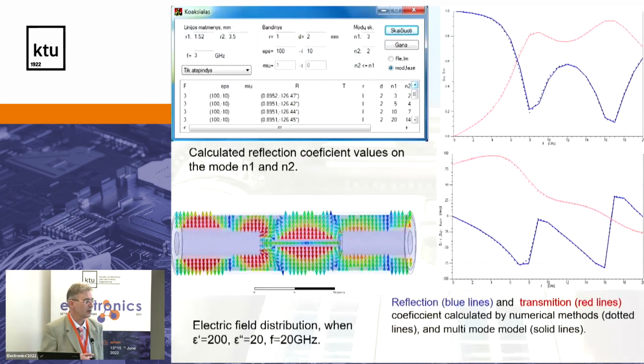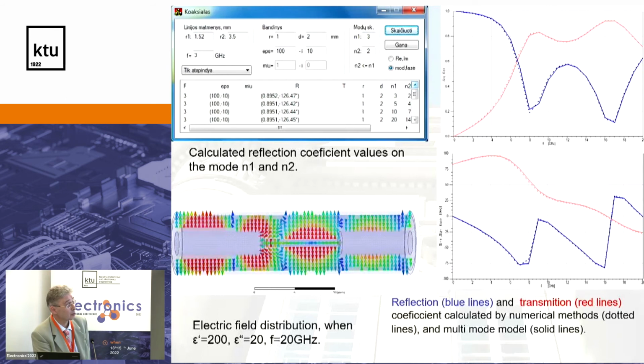The same method can be applied, that was for reflection type measurements. The same method can be applied, you have inner conductor, sample, outer conductor, and this region is treated again as a cylindrical waveguide with the dielectric inside it, non-homogeneous cylindrical waveguide. And we can see points are calculated with finite elements calculations, and lines are measured and they fit very well. So we showed that this model is really working, and to get more information, I have not written it here, but our paper was published in Review of Scientific Instruments on that.